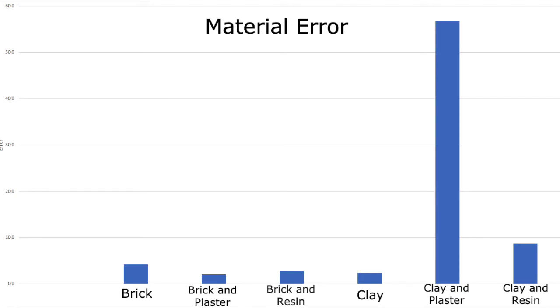In conclusion, using plaster as a medium to encase samples is a rather dangerous bet. If you know your specimens will have a very strong signal, then maybe it doesn't matter. But most materials that need to be encased in plaster are actually very weak, like the clay we used in our experiment. We showed that synthetic resin, on the other hand, is almost entirely invisible and can be used even on the weakest of specimens.